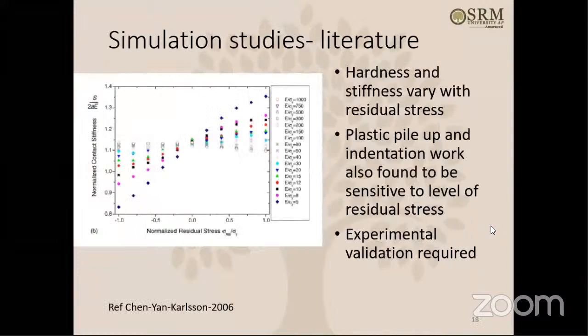So let's see. Some FEA simulation studies were done in the literature, trying to find the effect of changes in residual stress on the stiffness and hardness of the material. This is just one example. They used materials with different yield strengths, varying over a large range, from very low to medium to high yield strength. Artificially, they created residual stresses in the FEA model, and then did indentation in the model, and saw how the stiffness varies as the residual stress varies, and also how the hardness varies as the residual stress varies.